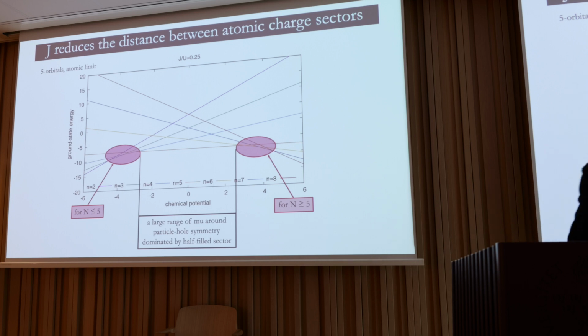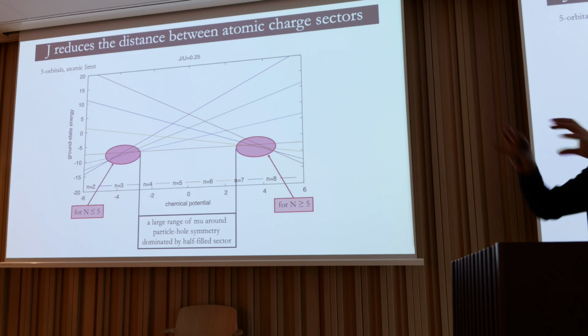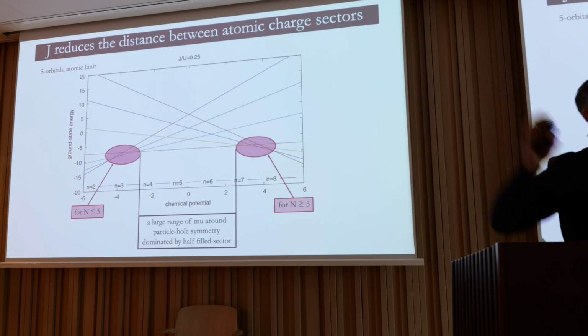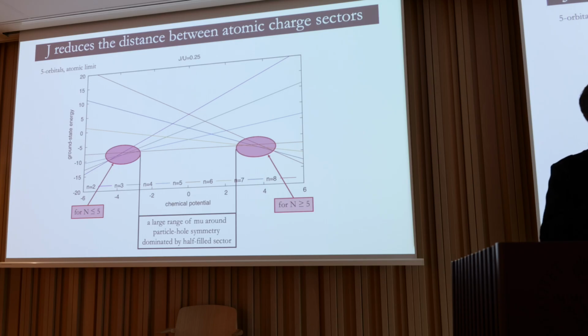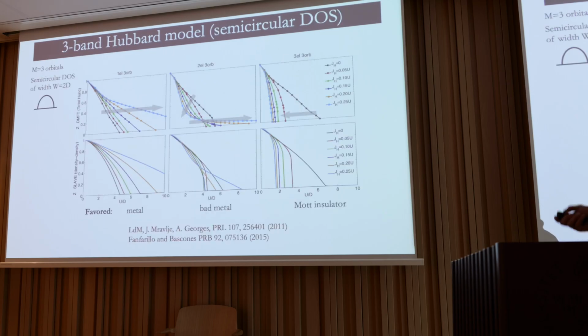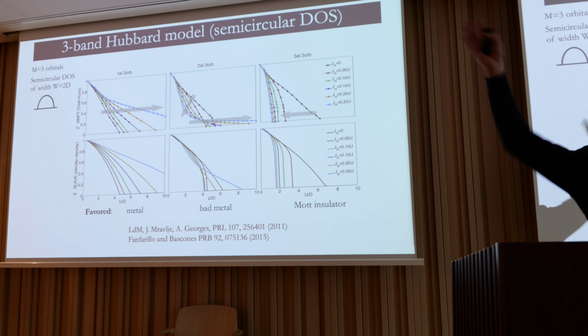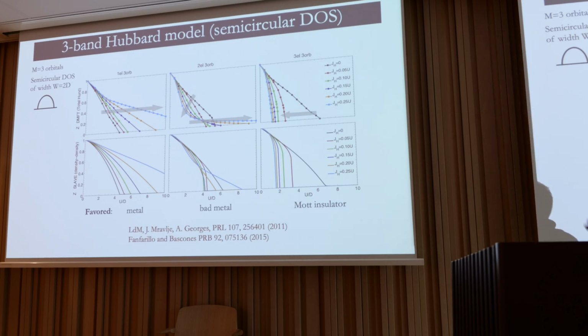So these two effects can collaborate: the distance between charge sectors, the easiness of the charge fluctuations, and the number of configurations in the ground state that you can combine to make the quasi-particles. They can collaborate or fight among them, depending on the average filling of the material. We made a little classification with Antoine Georges and J. Mravlje, and we distinguish the half-filled case, where the two effects collaborate to make the system more correlated, because they reduce the ground state degeneracy and they send all the charge fluctuations to high energy.